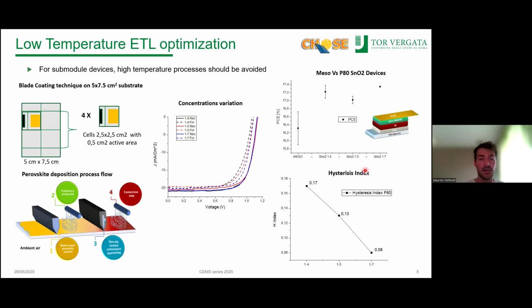So I will just go quickly through the optimization of this ETL, which is just tin oxide nanoparticles dispersed in water. The stack is the same, the process is the same, and the substrate is the same. But in this case, we move to large area cells. So for each piece of glass, we have 4 cells of 0.5 square centimeter active area. We optimized several parameters like speed of the plate, temperature of the plate, temperature of the air, concentration, and height of the blade, and with this optimization, we got a compact and uniform tin oxide ETL at low temperature, below 160. We annealed it at 150 in ambient air with a peak efficiency above 17%.